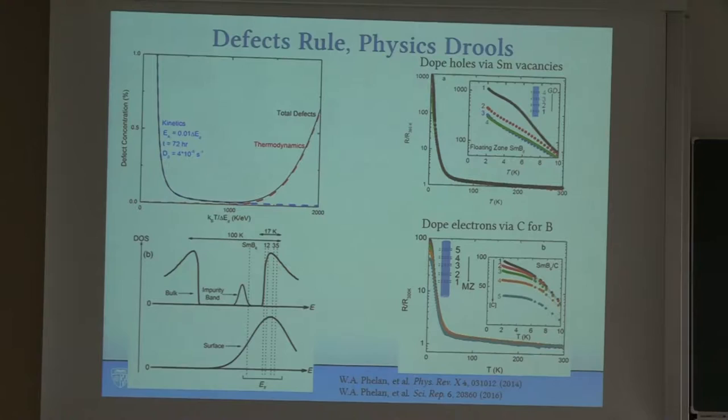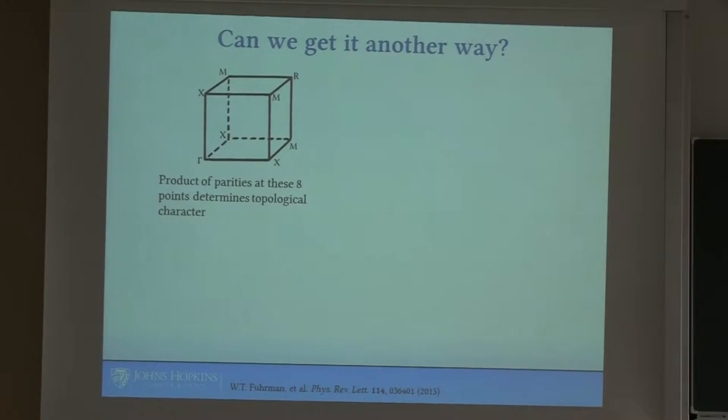And so this is great, this is wonderful, but is it really a topological insulator? Because none of this actually tells you that. And that's actually exceedingly hard to figure out in this material, in part because the band gap is very small. And because the band gap is very small, it's very difficult to do ARPES with sufficient energy resolution to get conclusive data.